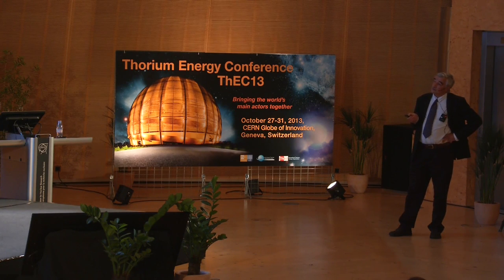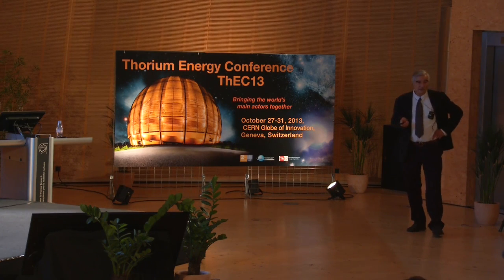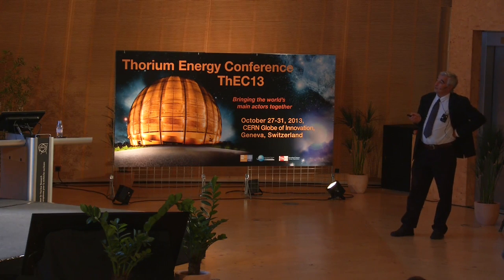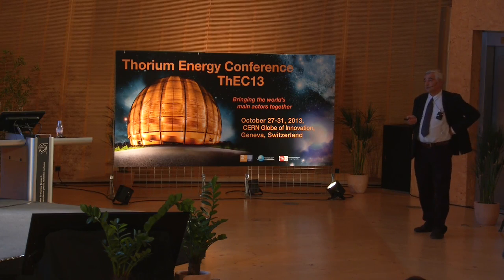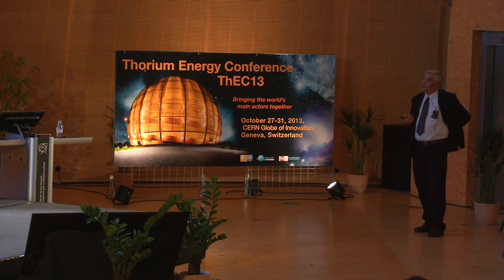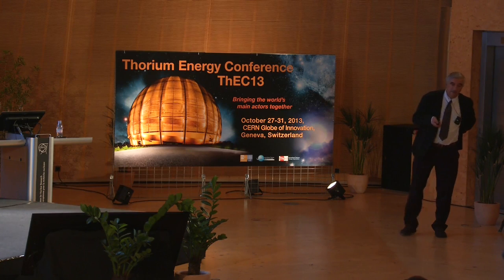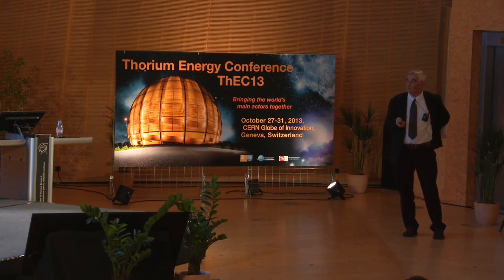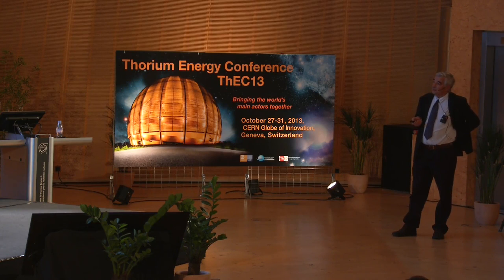There was a test requested in order to check what would be the behavior of the target in case of a leak at the window. So this so-called full-scale leak test was performed in a very short time at PSI in order to provide some information to the safety authorities, and particularly also to test the LBE leak, to detect this leak with a device based on AC impedance, which was also developed by PSI.